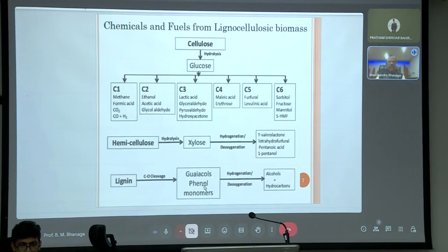So, what type of chemicals and fuels can we produce from lignocellulosic biomass? As I told you, cellulose via hydrolysis can be converted to glucose, and glucose becomes a platform for a variety of C1 to C6 building blocks. So, if you consider C1, you can get methane, formic acid, CO2, syngas. In case of C2, you can get ethanol, acetic acid, glycolaldehyde. C3 gives you lactic acid, glyceraldehyde, pyruvaldehyde, hydroxyacetone. C4 is malic acid and erythrose. C5 gives you furfural and levulinic acid. C6 gives you sorbitol, fructose, mannitol and 5-HMF.